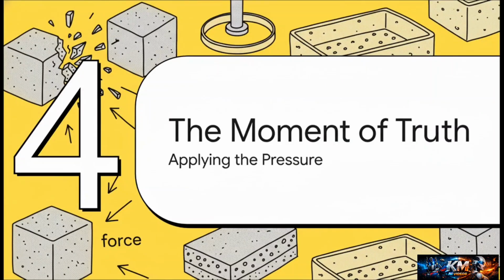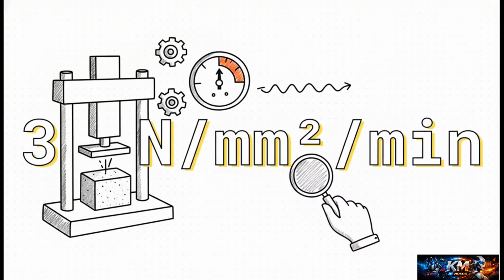All right, after all that careful prep and waiting for the cubes to cure, it's time for the main event. This is the moment of truth. This is where we find out if all our hard work paid off. It's time to apply some serious pressure. And here's another number you absolutely have to get right. 3 newtons per square millimeter per minute. That's the speed at which the compression machine has to apply the load. It has to be constant. If you go too fast, you'll get a fake high number. Too slow, and the result is just wrong. Like everything else, precision is key.